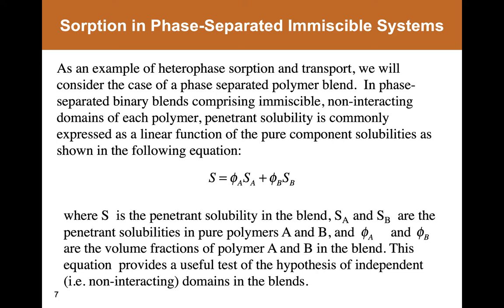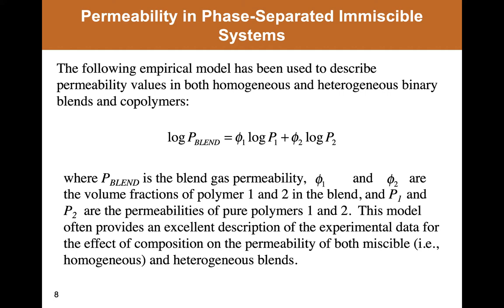And because polymer blends are used in a wide variety of applications, there have been many studies of transport properties in polymer blends. And often the data are found to obey a very simple empirical model that's shown in the middle of this slide. And that is that the steady state permeability in the blend, the logarithm of that, is given by the volume fraction weighted logarithms of the permeabilities of each of the two polymers in the blend. Now, there are theoretical discussions about when this empirical model applies, and one can see slight deviations away from it, but often this would be the first place to start in trying to model or to predict what the permeability would be of a blend of two different materials.